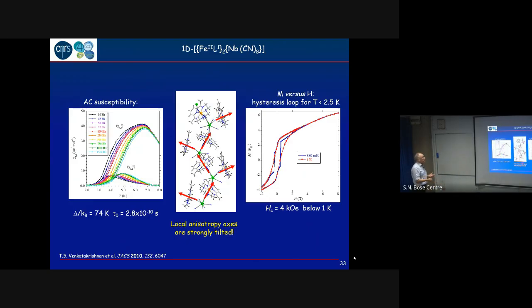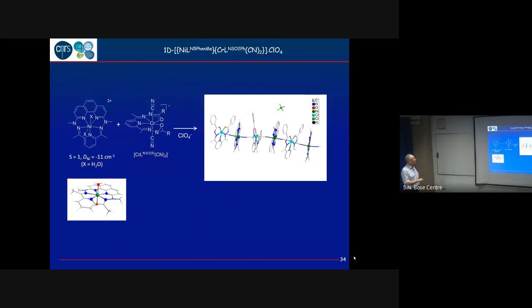So what was clear here is we have to align the magnetic anisotropy of the cell. And actually, this was done by using this building block I have already introduced before. So why? Because in this case, we have a perfectly trans cyanometallic. So if this piece is linking other pentagonal units, it has to be linear.